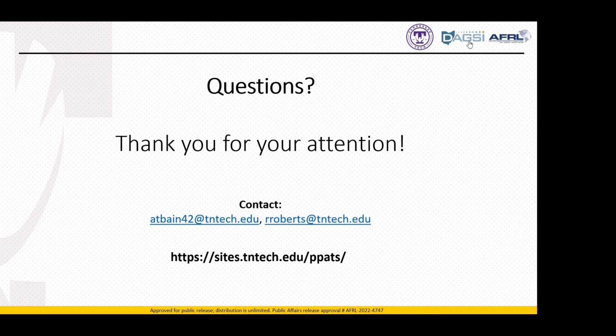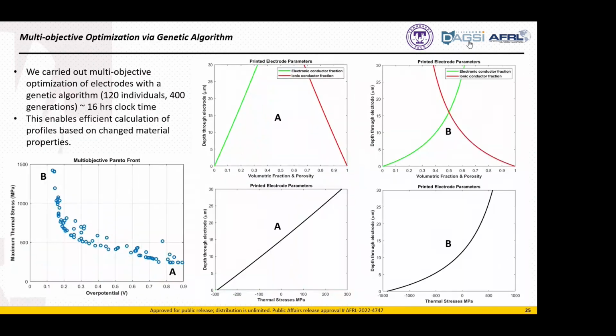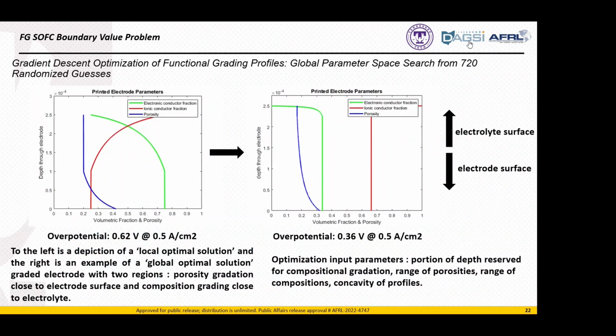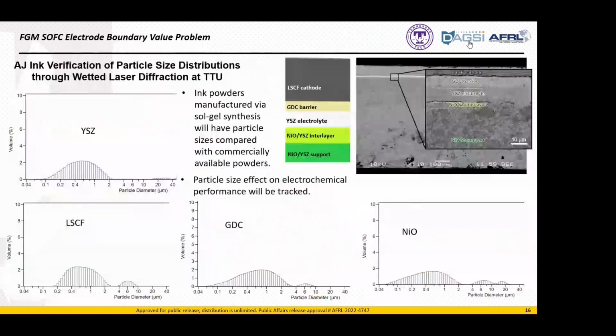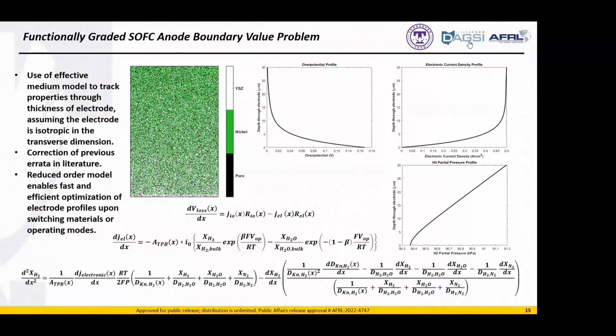the ability to model different materials such as the lanthanum strontium manganites, which have almost no oxygen diffusion, right? The diffusion is very low within the material, versus lanthanum strontium cobalt iron oxide, where there's significant oxygen diffusion. So there's a significant two-phase interfacial effect. So that's very good. I just caution you when you present that you don't say that we're implying that this is all just about electron transfer as a rate limiting step.